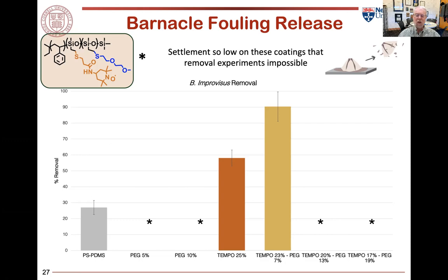And if we look at the TEMPO PEG combination, we see that partnership is very effective in even inhibiting the settlement, but also enabling release. So any cyprid that tries to settle and grow there has a hard time doing it, but any that's there is weakly attached. Now, we also know that the higher the PEG, the better and more effective this is going to be.